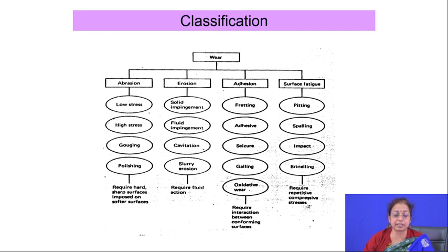You can collect the debris as well as the surface, then you can go for X-ray diffraction analysis to know what phases are present in the debris as well as what phases are present on the surface. And you can also do micro hardness measurement on the surface to see whether there is any change in hardness. But typically if you do scanning electron microscopic observation and X-ray diffraction technique, you get the idea about the mode by which the wear proceeded in your case.